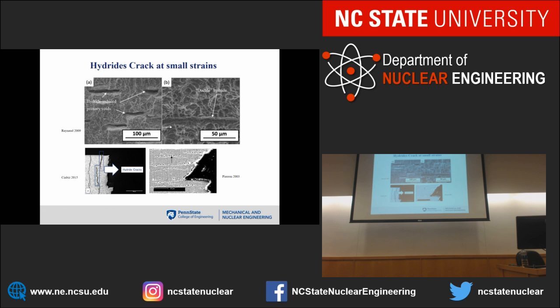So what we notice if you do the fractography is that the hydrides crack at small strain. This is tested at room temperature. This is tested at 300. Look at the hydrides here. And you create, you know, when you crack, they'll do this. You look at this. This is the fractured surface right here, and this is an uncracked hydride. One obviously cracked here, but there's a couple that crack here and here, right? And if you look at the circumferential hydrides, they have these little voids that are formed. And if I walk away from the fractured surface, I can determine the critical void nucleation strain that I can measure, right?